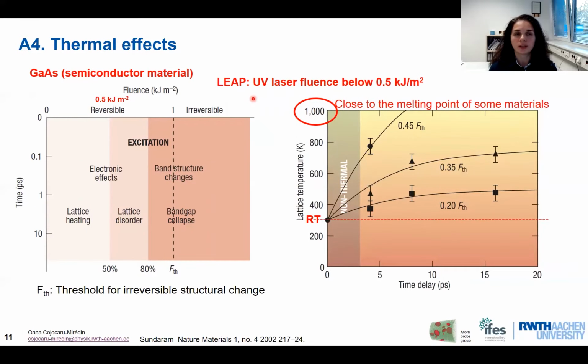The fourth mechanism that we were talking about is the thermal effect. There is very nice work done by Sundaram and published recently in Nature Materials. They have shown that the laser fluence is a very important parameter. If the laser fluence is too high, then we reach a certain threshold for irreversible structural changes. It means that our material is going to be completely changed structurally. The band gap is going to collapse and the band structure is going to change. Now, the LEAP has a UV laser fluence below 0.5 kilojoule per meter square, which means that we are not reaching these irreversible processes. So this is a good message for us.